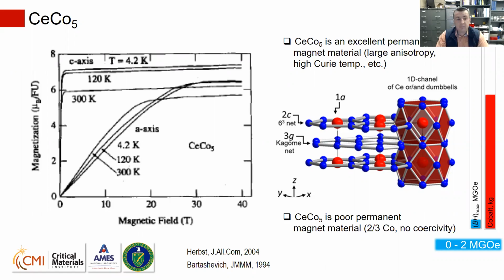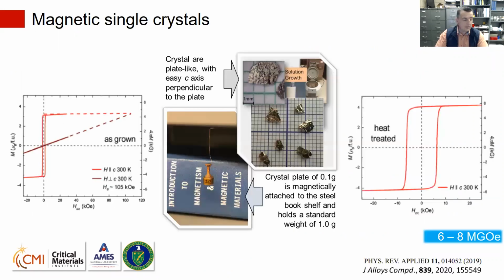But we decided that maybe we can still make it practical. And everything changes if you admix a little bit of copper into cerium cobalt 5. The changes amaze you, because we grew single crystals of these types of materials, and we found that a crystal plate of 0.1 gram, basically 100 milligrams of the material, can actually hold 1 gram of weight. This is what you see in the central image of this slide. This is amazing and not trivial, because usually single crystals don't have extrinsic magnetic properties. And even here already, we developed 6 to 8 megagauss oersted.